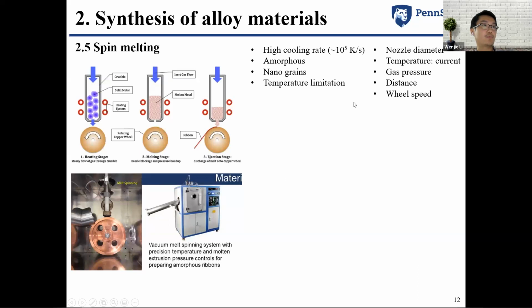In principle, this spin melting can provide a high cooling rate up to 10^5 Kelvin per second, which can produce amorphous alloy materials that can benefit further nanostructuring and nano engineering of the bulk materials. But this method also has a temperature limitation based on how the crucibles are designed and how reactive the materials used are, which can be achieved by the induction melting method.